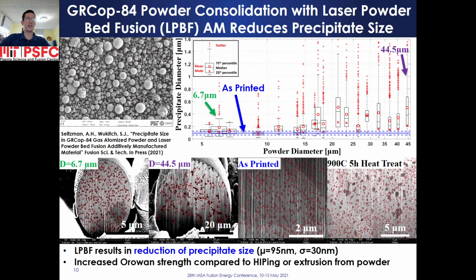Consolidation with laser powder bed fusion results in a reduction in precipitate size during the LPBF process by either breaking apart precipitates within the powder or dissolving them into the melt and reprecipitating them during the rapid resolidification of the laser melt pool. The resulting precipitate distribution is smaller than the precipitates within the initial powder stock.